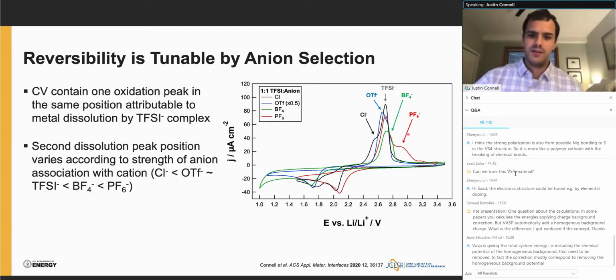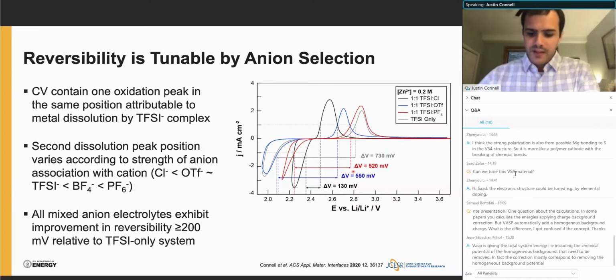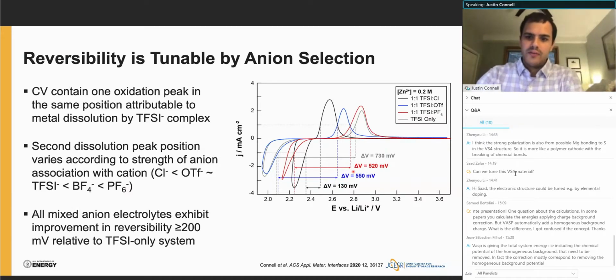And interestingly, in the case of PF6, we also see the onset of reduction start to creep more positive of that of the TFSI only system, which is, again, consistent with this idea, because with a more weakly coordinating PF6, it should be easier to desolvate zinc cation or desolvate cations relative to TFSI. And again, as we saw before in the TFSI triflate case, all of these mixed anion electrolytes result in improvements in reversibility relative to the TFSI only case.